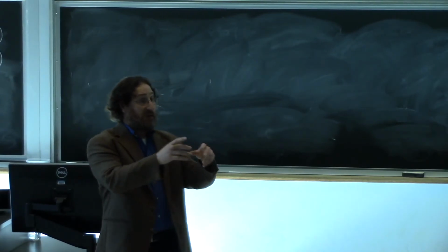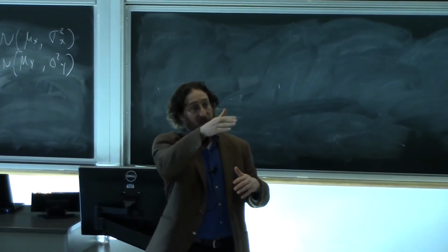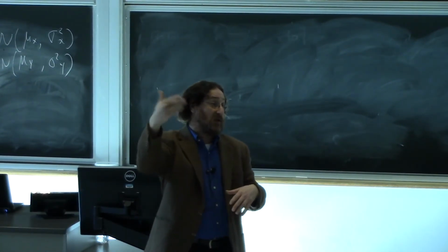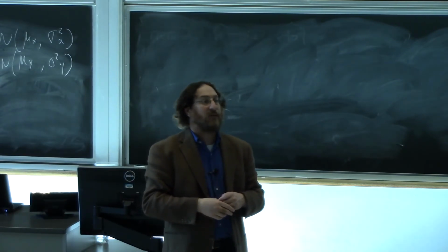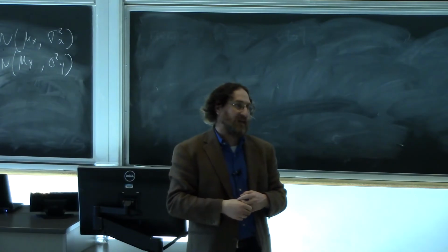And so ultimately what we wound up doing is getting a more relational result, seeing that I have a certain amount of plating and I have a certain capacity fade, drawing an empirical plot and getting a fit to that, showing that with this much capacity fade I should expect so much plating in the system. But I wouldn't say it's fundamentally based, it's more empirically based from the data that we collect.